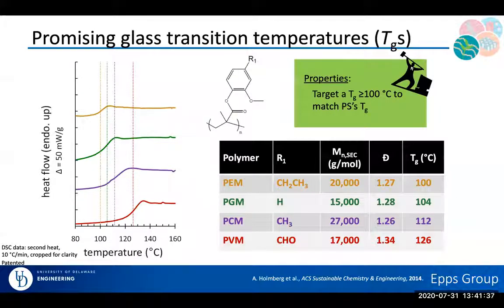The first thing that we did is we took the individual molecules that were on the previous slide and homopolymerized them. So we have structures shown here where the R groups are basically things like a vanillin, so an aldehyde group, a methyl group, an ethyl group, and so on. We can do differential scanning calorimetry. The curves are shifted vertically for clarity, but the key point is shown in the rightmost column. Once we polymerize these materials, we can see that we have glass transition temperatures at 100 degrees or even slightly above.